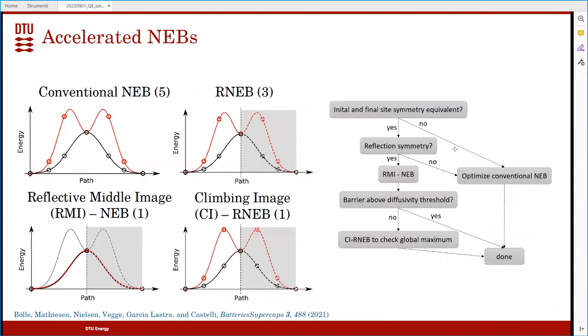But then we can further accelerate that, because in most cases the middle point is where you have the transition state. So you calculate only the initial point, the final is reflected, and then the middle. For those of you that work with multivalent cations, you're aware of the dumbbell shape of the barrier, right? But then you know that the barrier cannot be lower than this point. So if you already know that the diffusion is bad, you can discard it. But if the diffusion is good, then you can do the reflective NEB and get the real transition.